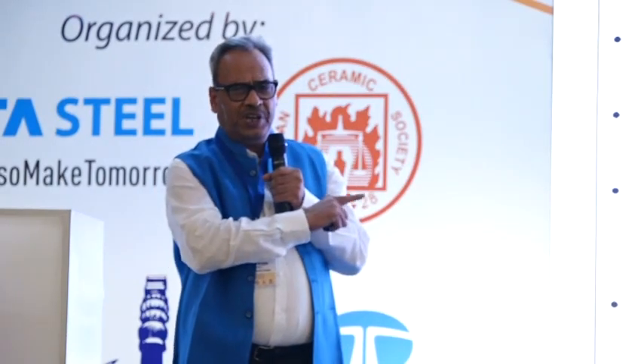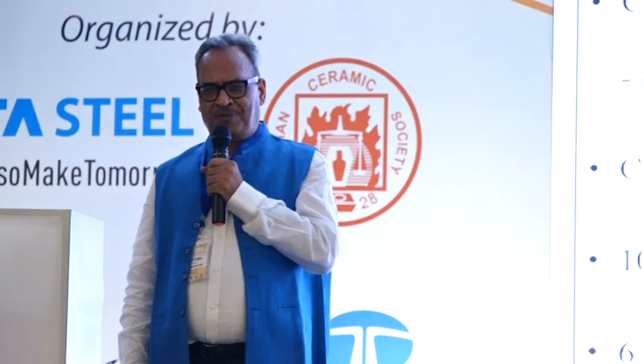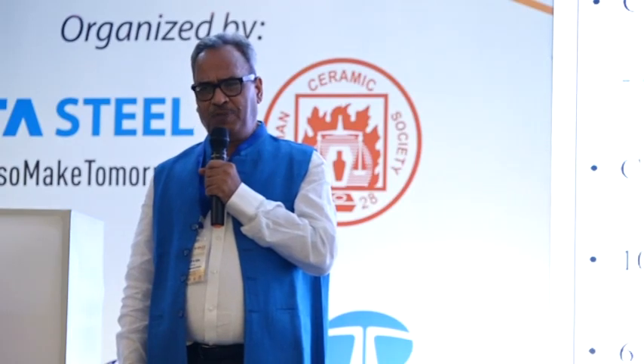is not increasing the free lime percentage in cement, perhaps because of the grinding. First, the dilution effect, and second, because of the finer grind, it could have absorbed moisture from the air and converted it into calcium hydroxide. This report has been submitted to the Bureau of Indian Standards, and it is at an advanced stage of discussion. The cement industry has some observations, and the feedback from the cement industry will be discussed at BIS level, and then perhaps it will go through.